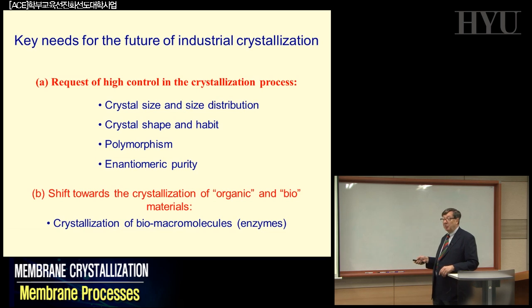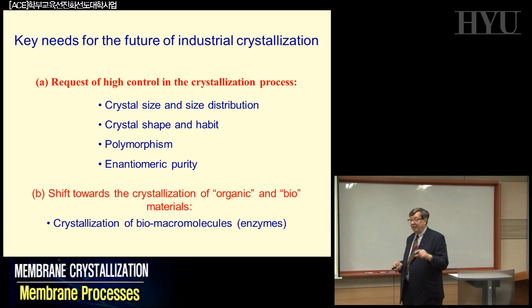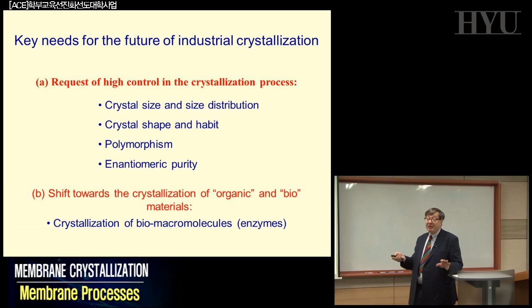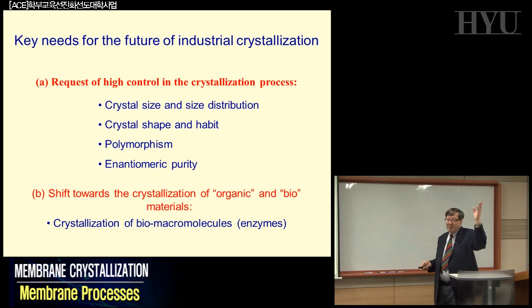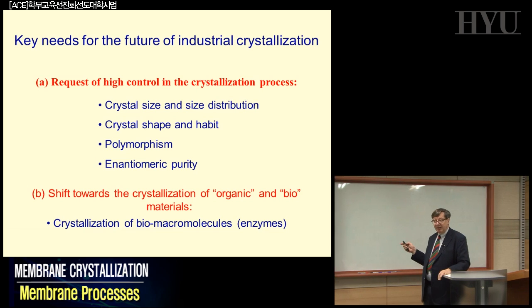So the enantiomeric purity is one of the key issues. When you buy any drug, you have to read on the label, on the back, which today by law states which level of enantiomeric purity is present. And if it's 99.9, you are pleased. If 50%, you must be worried. And what is the other 50? Normally for the other 50, we have no evidence of any negative effect in 10, 15 years of experiments. We never know what will happen in 300 years. And that is one of the problems still existing.